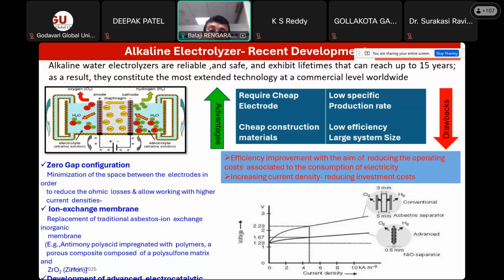But if you want to produce more hydrogen, you have to increase the number of cells. You cannot increase the area of the electrode, because you have a current density restriction. You cannot pump more than 400 milliampere per centimeter square. If you give more current, then obviously the electrode will undergo corrosion instead of evolution of gases. That is the bottleneck of this alkaline electrolyzer, so the system size will be higher.